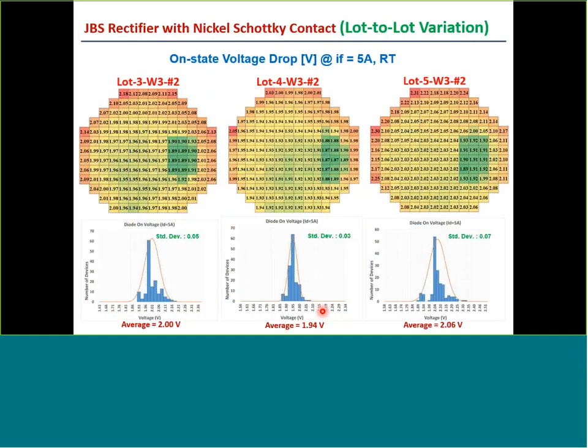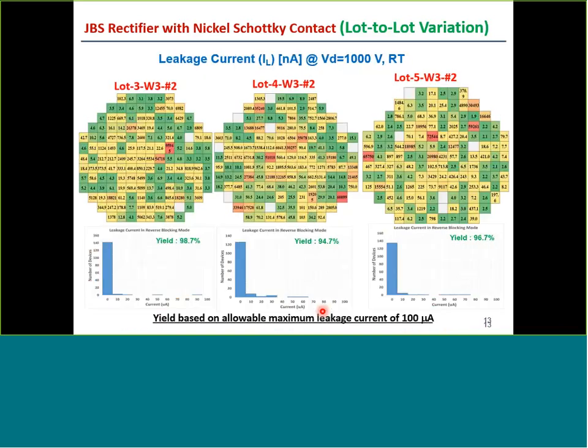In terms of lot-to-lot variation, this slide shows wafers from 3 lots, and once again, the distributions are very tight, and we have good reproducibility. Same holds true for the leakage current. The leakage currents are also in nanoamp range for all of these wafers, and well below the 100 microamp spec.